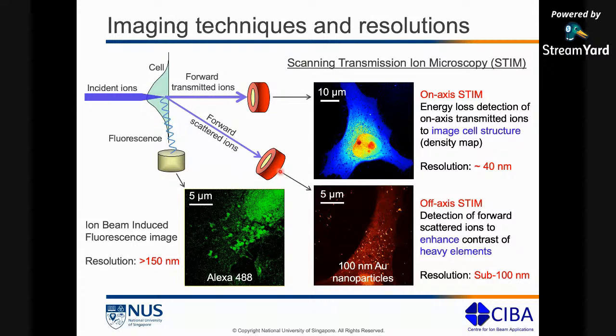Okay, and then if you look at the two images, this is the image taken from an on-axis STIM, that is from this detector. This is the one taken from this detector. The resolution of the on-axis STIM image is extremely good. We typically get about 40 nanometers of resolution for on-axis STIM images. But the downside is this detector faces the ion beam, or is right in the path of the ion beam. So by keeping this on-axis for a long time, you are reducing the life of the detector. If you keep on taking on-axis STIM images, eventually your detector will get damaged.